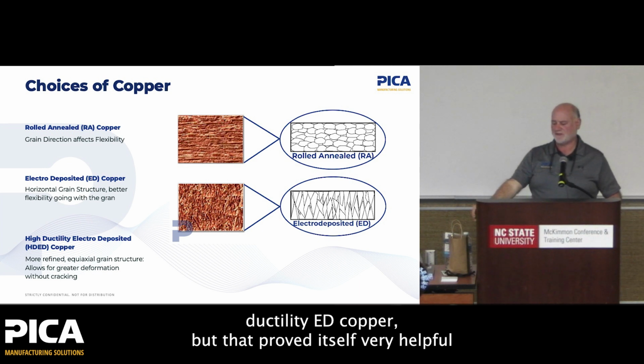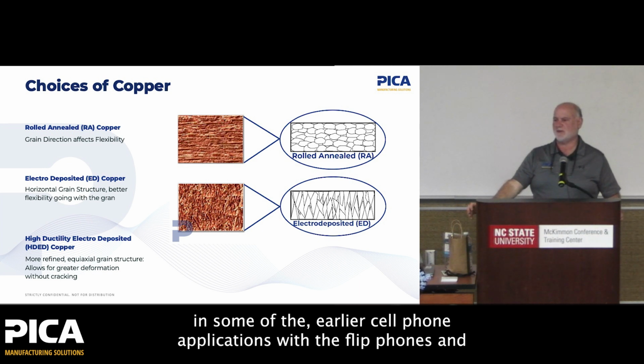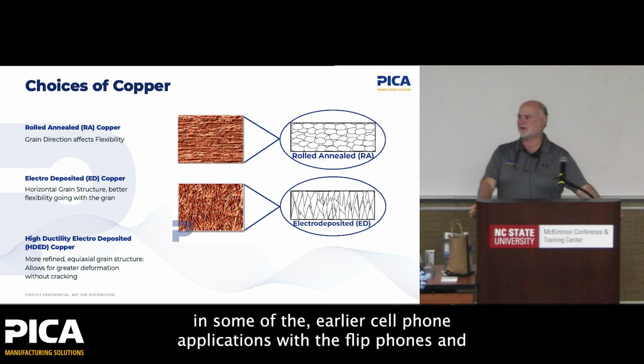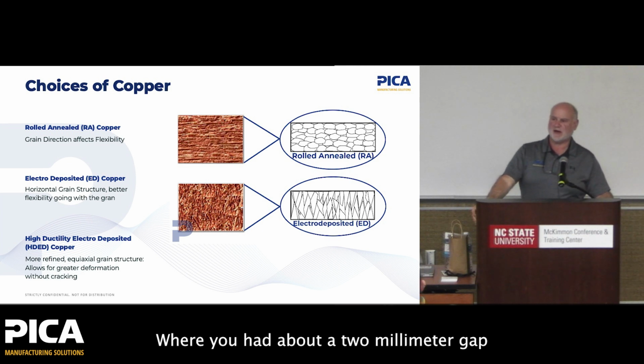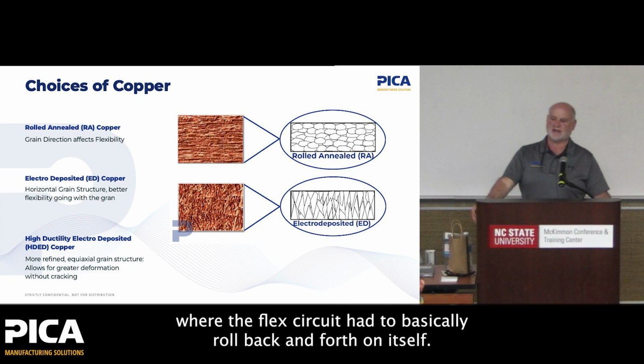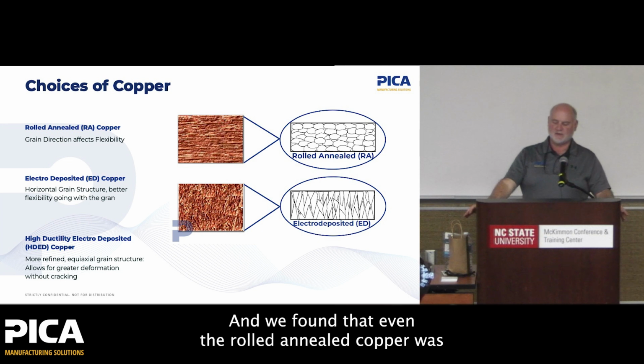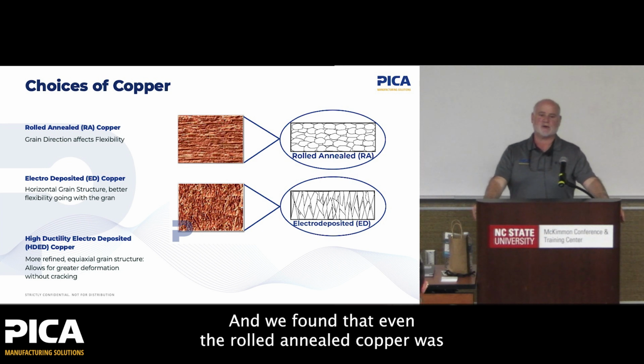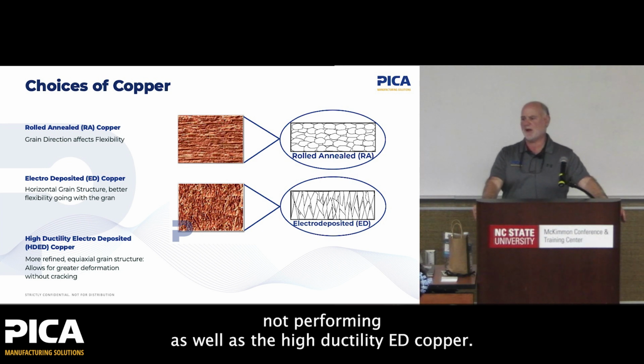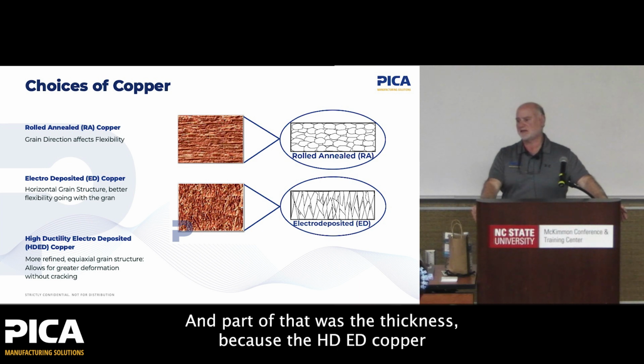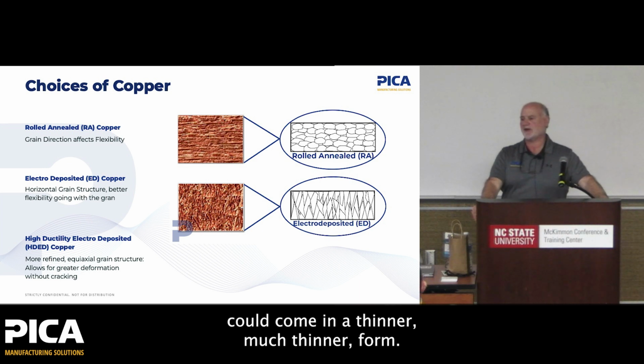Now there are, I don't have a picture, unfortunately, of the high ductility ED copper, but that proved itself very helpful in some of the earlier cell phone applications with the flip phones and the slider phones, where you had about a 2 millimeter gap where the flex circuit had to basically roll back and forth on itself. And we found that even the rolled annealed copper was not performing as well as the high ductility ED copper.